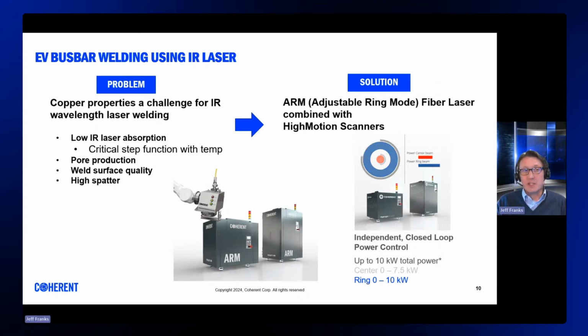It was quickly recognized that the issue with other high brightness IR lasers could be overcome by employing our patented independently controllable ring beam, which can suppress spatter and pore production through preheating and extension of the melt pool behind the keyhole.